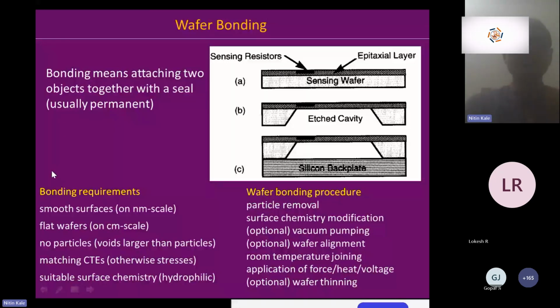Wafer bonding is the method to stick two wafers. It could be done either through thermocompression, or it could be done through some sort of anodization or electroanodization. It is very necessary that the surfaces are very, very clean. They're flat. Only then the adhesion is good. And the wafers also have similar TCs.